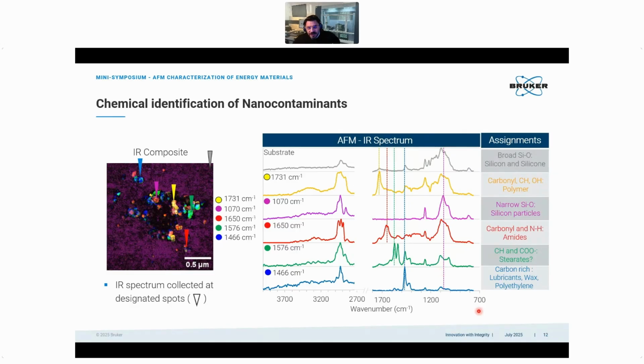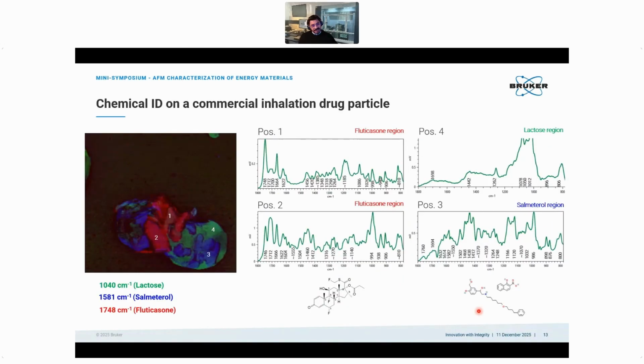I like this example because this is done out of a test, and I've told you that I will show this earlier. So basically, my colleague, Dr. Stadler, just went out to the pharmacy and got an inhaler drug, and then actually prepared the sample with these particles inside this inhaler drug and looked at them in AFM-IR. So you see these particles in here, and you can identify with different contrasts obtained at different wave numbers. So each color here is obtained from an AFM map where the laser pulse was sent at one given wave number.